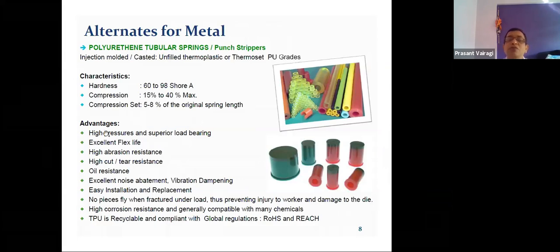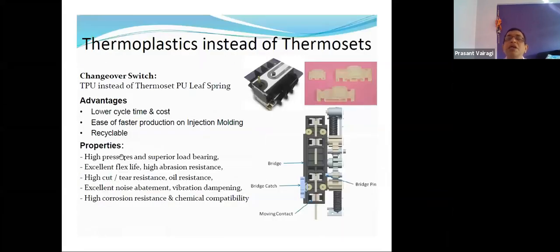Now the beauty of this material is this is actually covered within the housing and bridge cross section. Earlier, we had designed this with thermoset, considering the arc aspect and all. But then, considering the lower cycle time, that is productivity from the thermoplastic aspect, lower cost, faster production rate, recyclability, we have now introduced thermoplastic polyurethane, which is working very fine.